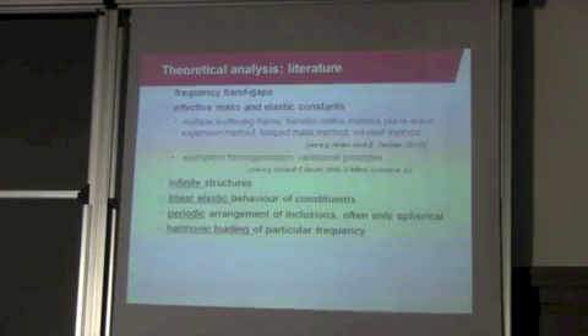In the last 15 years, there has been quite some work on the analysis of these materials, mostly in the physics community, but also quite some work in the mechanics community. Claude gave us an excellent overview of this work yesterday. However, almost all methods used for this analysis have to assume infinite structures, without considering the effects of finite sizes and corresponding boundary conditions. You can always ask yourself what will happen with this local resonance effect if it starts interfering with the boundaries. Usually linear elastic behavior of the materials has to be assumed. Some of the methods have to assume periodic arrangements and only simple geometry, such as only spherical inclusions. And often they can only consider particular types of harmonic loadings, usually at a frequency selected beforehand.